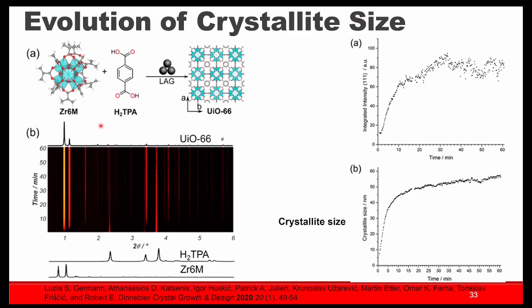This is a synthesis of a MOF called UiO-66 from this zirconium hexanuclear cluster with this terephthalic acid linker. And what I found was really interesting is you get nice diffraction patterns of the MOF forming. And Lucia did a bunch of Rietveld analysis and, using the Scherrer equation, was able to estimate the crystallite size. And one of the things that I think is really important to note in the synthesis is that the crystallite size is increasing of this UiO-66 phase as it's forming, but then it becomes relatively stable over time.